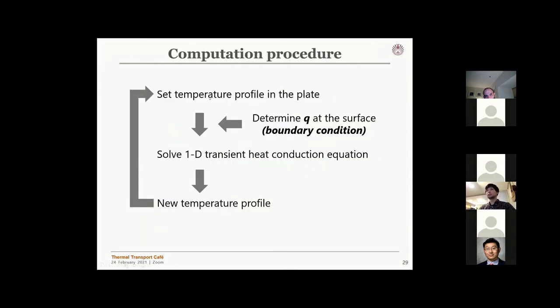This is the computation procedure - not that complicated, I guess. First we set the initial temperature profile in the plate, then give this boundary condition of heat flux, determined by the model presented earlier, and solve the 1D transient heat conduction problem to get the new temperature profile. Then we use this new temperature profile to set the new initial condition, and repeat this calculation until the surface temperature reaches 250 degrees Celsius.